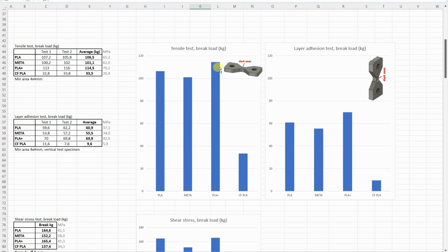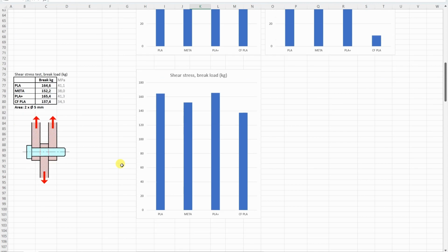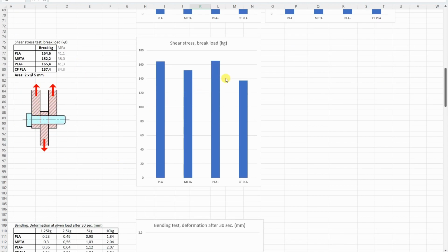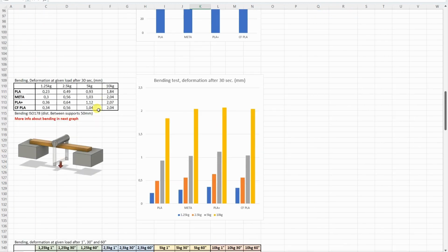Tensile and layer adhesion test. These three filaments are very similar, and actually they perform very well even on the layer adhesion test. Only the carbon fiber PLA was very weak even in the layer adhesion test, but also in this tensile or pulling test. On this two-sided shear stress test, as you can see, all four filaments perform very similarly.